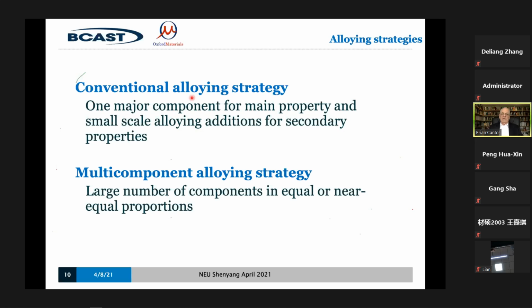But it's not just metals, it's also ceramics. You know, if you want window glass, it's silicon oxide, because silicon oxide is transparent if it's cooled reasonably rapidly from the melt. But you add actually sodium oxide because that lowers the melting point and makes it form glass a little bit more easily. And you add other oxides to give it strength. So this is true of every single material that we use. It's one major component with a few additions of a few extra small pinches of things to give secondary and tertiary properties.